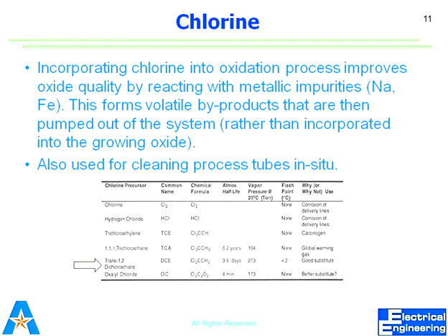If we supply chlorine gas, it corrodes the internal side of the pipelines or the cylinder, and takes those corrosive impurities with it towards the furnace. So chlorine as a gas is not a good source. The problem is corrosion of delivery lines.